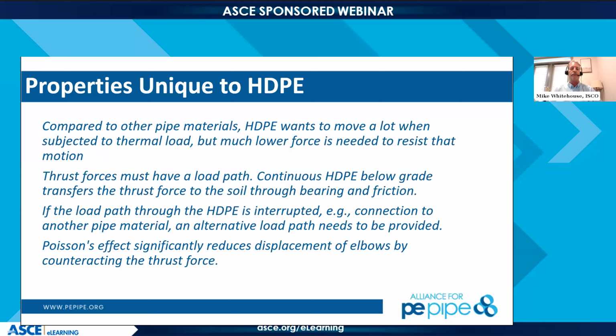In those applications, it would be prudent to use a very high or an instantaneous modulus because the material is going to be changing temperature very quickly. If the change is occurring slowly through seasonal, it's much more gradual, and typically 50 to 55,000 PSI is used for a seasonal change in the material, whereas more like 120 or 130 would be used for instantaneous. Another thing that I'll point out is since the polyethylene is self-restrained, it really doesn't hurt the piping material at all if it moves underground. In fact, it moves above grade all the time.